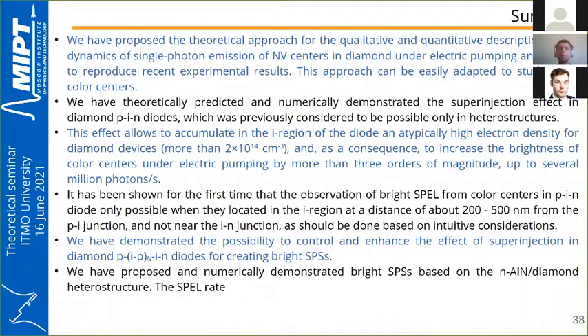We have theoretically predicted and numerically demonstrated the superinjection effect in diamond p-i-n diodes, which was previously considered possible only in heterostructures. This effect allows accumulation in the I region of the diode of an atypically high electron density for diamond devices, more than 2 times 10 to the 14 per cubic centimeter, and as a consequence, increases the brightness of color centers under electrical pumping by more than 3 orders of magnitude, up to several million photons per second.